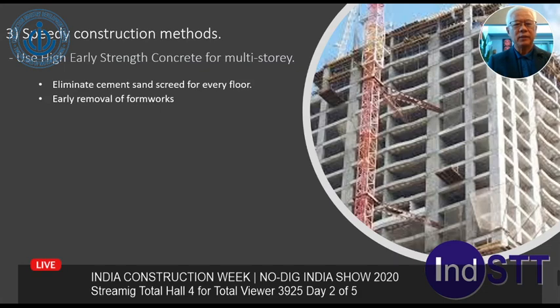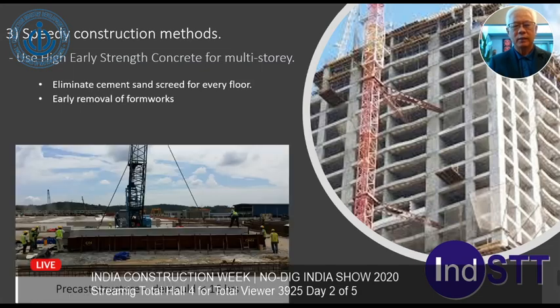And of course, the other thing is, if you use high early strength, you can actually save on your formwork, isn't it? As you know, if you do a multi-story building, you might probably need 3 sets of formwork or even 4, to speed up the work. So with high early strength, you can remove your formwork after 24 hours and reuse it, compared to standard concrete where you need about a week. So these are the reasons why the high early strength helps.